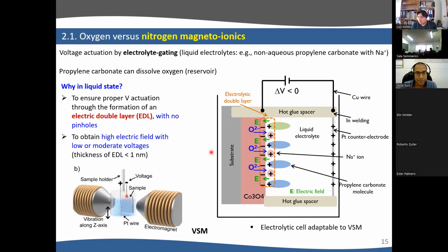Okay, now let's focus a little bit on what we do. All that I will present is using a liquid electrolyte, which is propylene carbonate. And this is a non-aqueous electrolyte. We want to avoid the redox reaction. We just want to induce exchange of nitrogen ions or oxygen ions between the layer of interest and the liquid without any extra redox coming from the liquid itself. So all the oxygen or nitrogen comes from our sample.